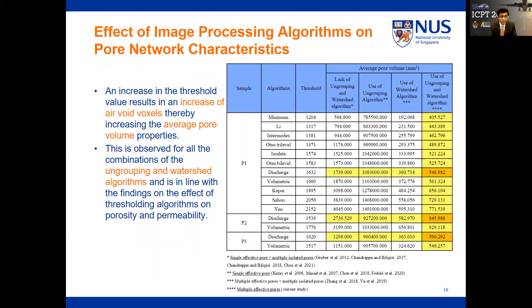We first investigate the effect of image processing algorithms on pore network properties, mainly average pore volume. The first column represents different samples, the second and third columns represent different thresholding algorithms, and the final column represents the average pore volume for different combinations of ungrouping and watershed algorithms. The lack of ungrouping and watershed represents a single effective pore and multiple isolated pores, whereas the use of the ungrouping algorithm alone represents a single effective pore. Use of the watershed algorithm produces multiple effective pores and multiple isolated pores, and the final column — the actual recommended approach — studies only the multiple effective pore structure. It can be seen that an increase in threshold value results in an increase of air-void voxels and thereby increases average pore volume properties, consistent with findings in past studies.